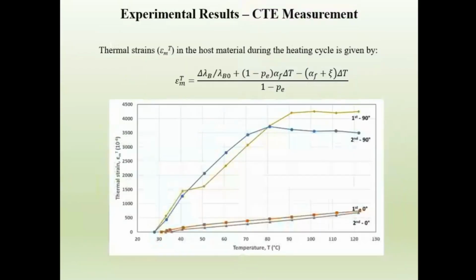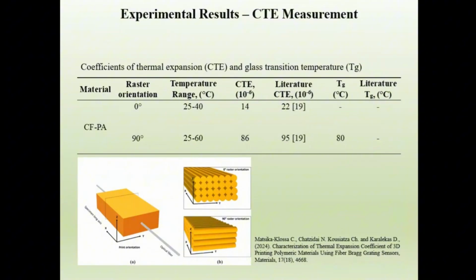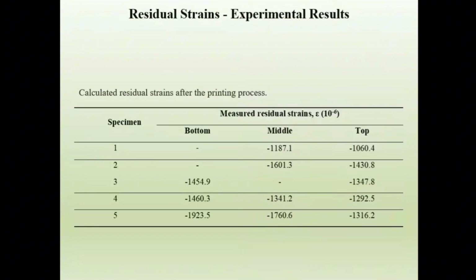And going quickly, in different specimens, by using the fiber optics, we were able to measure the coefficient of thermal expansion, with values very close to the ones that we found in the literature. And by using the same fiber optics in the specimens tested for mechanical testing, we're also able to calculate the fabrication residual stresses, the strains at the end of the fabrication process, at different layers of building. So you can see that the strains are of considerable magnitude, but they are very close to each other, with some differences between the bottom, the middle, and the top one.